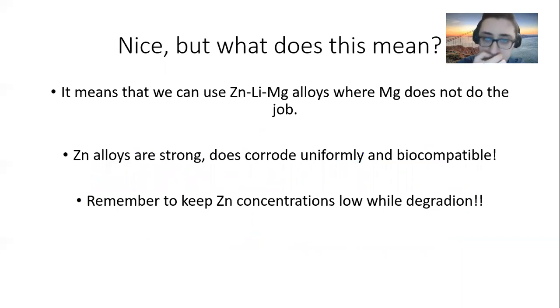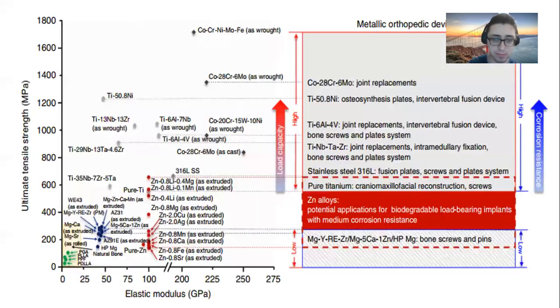Okay, so these were the findings, but what does this mean in general life? How are we going to utilize this in society? It means that we can use these zinc, lithium, magnesium alloys where just magnesium doesn't do the job, right? Zinc alloys are strong, and they degrade and corrode uniformly, which means they don't fail earlier than expected due to stress concentration. They're also biocompatible. That's very important too. But there's only one minor problem: we need to keep the zinc concentrations low while degrading because high zinc can be toxic. All right.